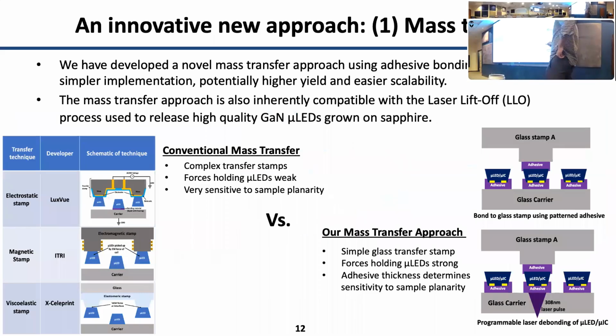So now, because of the various issues that I mentioned earlier, in this work we have essentially come up with two innovations that help us to overcome the issues. The first one is that we have come up with a novel mass transfer approach that uses adhesive bonding and has a much simpler implementation and potentially higher yield and scalability. And our mass transfer approach is also compatible with gallium nitride laser liftoff, which is used to release GaN micro LEDs on sapphire.